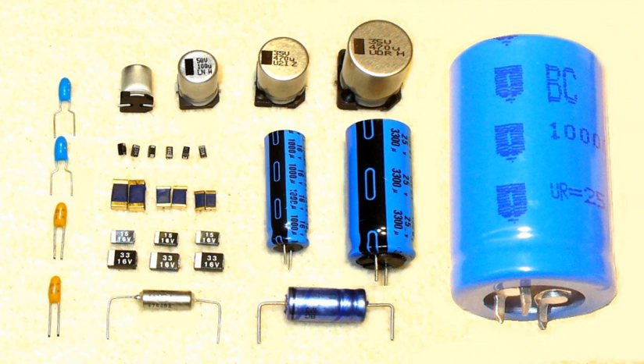These unwanted chemical processes depend on the kind of electrolyte. Electrolytes with water content or water-based electrolytes are more aggressive to the aluminum oxide layer than are electrolytes based on organic liquids. This is why different electrolytic capacitor series specify different storage time without reforming instructions. Applying a positive voltage to a wet capacitor causes a reforming self-healing process which repairs all weakened dielectric layers, and the leakage current remains at a low level, although the leakage current of non-solid ECAPs is higher than current flow over insulation resistance in ceramic or film capacitors. The self-discharge of modern non-solid electrolytic capacitors with organic electrolytes takes several weeks.